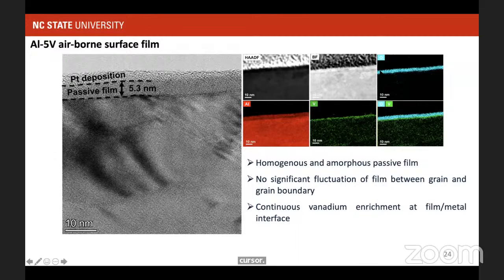So basically, we can see that surface film, and then we can study the different characteristics of the surface film. We can look at the crystal structure, the composition. We can look at the passive film and the metal interface. I mean, it's challenging. It's not an easy job to do, but we have the opportunity to do all the stuff, right? So looking at how this composition looks like, one thing we really realized was, if you look at these figures here, look at the one I'm showing here with the cursor. So it is a 5.3 nanometer thick passive film, and the way we verify whether it's oxide or what that is, there is a huge amount of oxygen present. So there should be either oxide or hydroxide, and things like that, right?